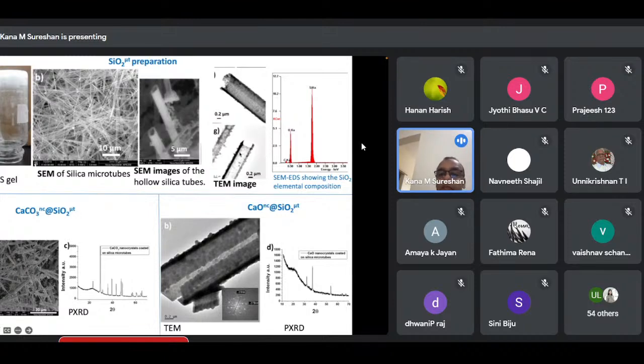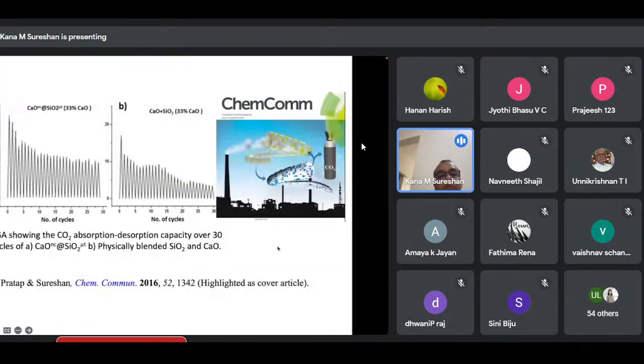And what you are seeing here, the small globules, are the calcium oxide crystals which we have grown. Here also you can see a TEM image, where you can see the calcium oxide nanocrystals in the tube. And this we have used. This has about 33% of calcium oxide, remaining is silica. We have used it for carbonation, decarbonation.